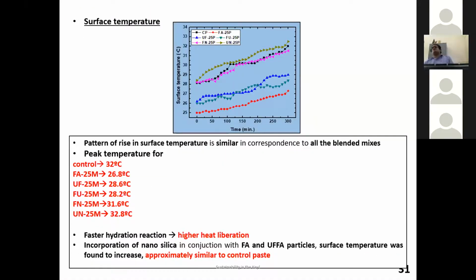Same thing for the surface temperature. But as you know, when I add nanoparticles, surface temperature is going to increase because of higher heat liberation. That is the key actually. Now what you can see here, the moment I'm adding fly ash, the temperature is reducing by around 5 degrees, 5.2 degrees, which is significant. That's why we are recommending fly ash to be used for the mass construction sector. That is the reason.